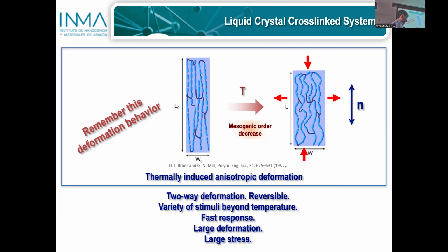If you cool down the system, the order of the liquid crystal is recovered, and due to the memory imposed by the cross-links, you recover the original shape. So they are reversible systems. Advantageously, you can use a variety of stimuli, as we will see later with some examples. They have a relatively fast response. In the case of elastomers, they show a relatively large deformation, and they can exert a reasonable amount of force, bearing in mind that they are soft materials, of course.